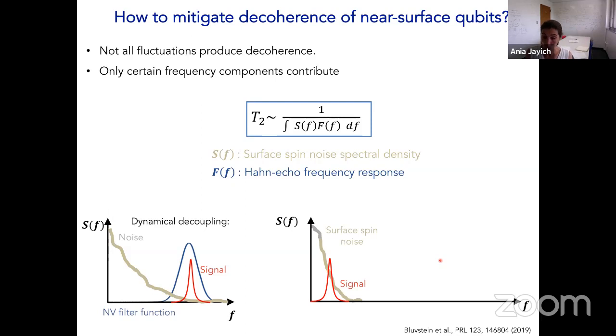I'd say one can improve. There's a lot of room to improve NV centers, in particular in this high spatial resolution limit, by addressing these surface-induced decoherence and using some of the techniques that I've talked about. On the squid side, of course, if they continue to make things smaller, they can get higher spatial resolution. But my main comparison is that NV centers offer higher spatial resolution. In terms of pure sensitivity numbers at this point, if I had the choice, squids would be superior. But if you're really trying to get nanometer scale spatial resolution, I don't see that happening anytime soon with squids. That's the kind of problem where it's useful to use NV centers, and also for the wide temperature range.